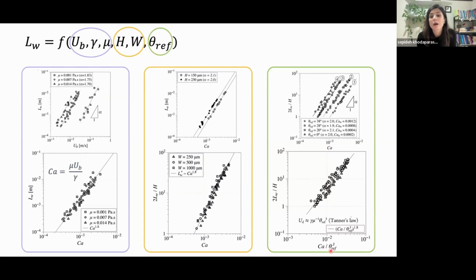So we decided to add this correction term to the capillary number and divide the capillary number by theta, which is some sort of a contact angle. This is quite an arbitrary number in our setting. I can explain it later, but over this theta to the power 3. And you see that all of the data collapses onto one single curve. And there is this power law, this corrected capillary number to the power 1/3.